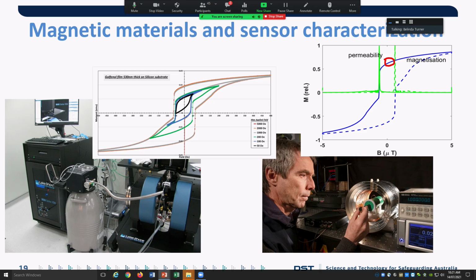This gives us a huge amount of information - this tells us not only how the magnetization behaves in the presence of a magnetic field, but also how you can control that magnetization, and how it depends on the history of the magnetic field it's been exposed to in the past. And based on this information, for example, we can extract data that is very useful for optimizing a magnetic field sensor.